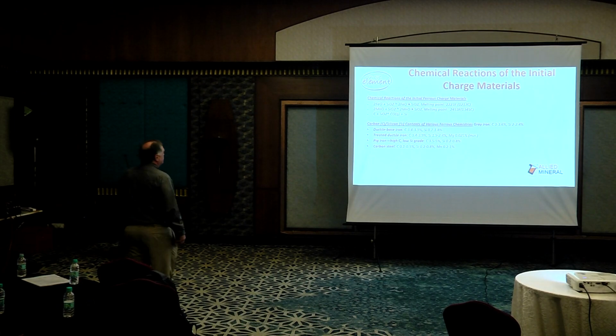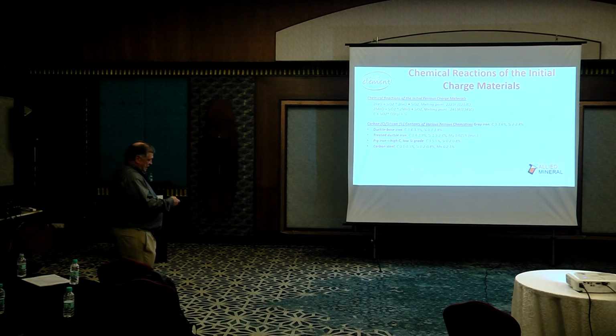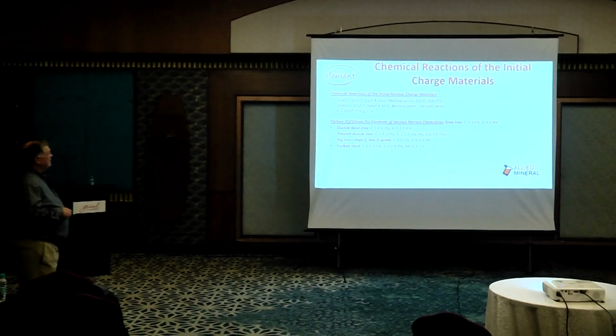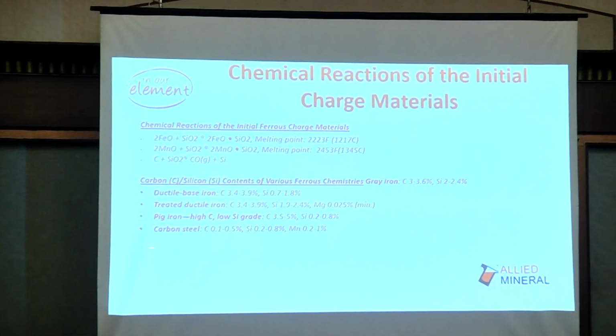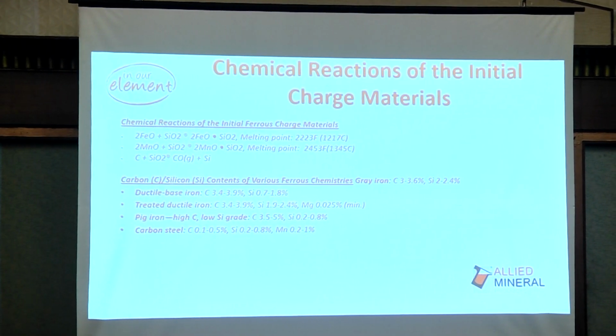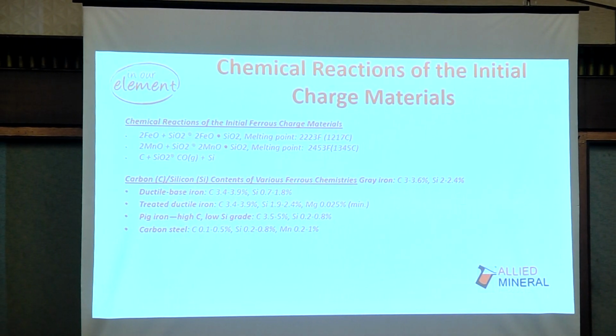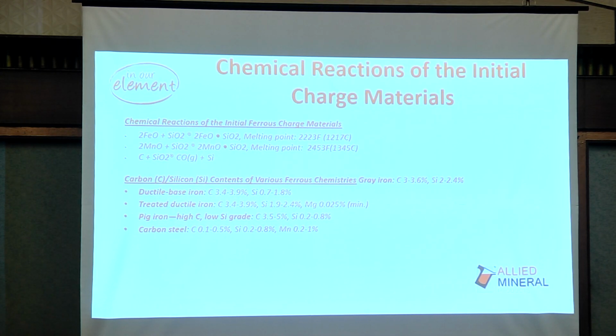Chemical reactions of the initial charge, as you can see here, here's what we're talking about. In ductile-based iron, you're right around 3.4 to 3.9 carbon, 0.7 to 1.8 silicon. Treated ductile, 3.4 to 2.4. And here's pig iron, 3.5 to 5 carbon, 0.2 to 0.8 silicon. Carbon steel, 0.1 to 0.5 carbon, silicon 0.2. When you start getting down into these, you have big issues because it does take the silica, and it's going to take the silica from the bottom first because the bottom's going to be higher temperature. It's going to be more skewed chemistry, and it's going to come out quickly.